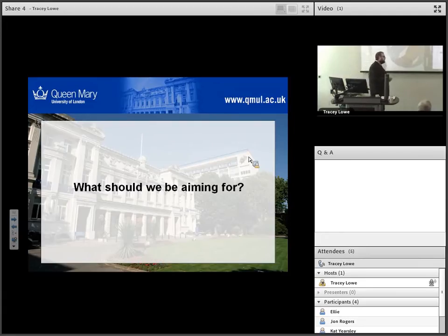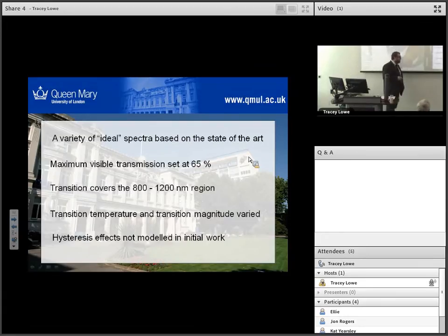Well, we decided to approach this by doing some modelling. Essentially we used a bunch of ideal spectra based on things that we thought were achievable in the lab. We've set some arbitrary targets such as visible transmission is set to 65%, and various different things. In the initial work, we didn't worry too much about the hysteresis effect.